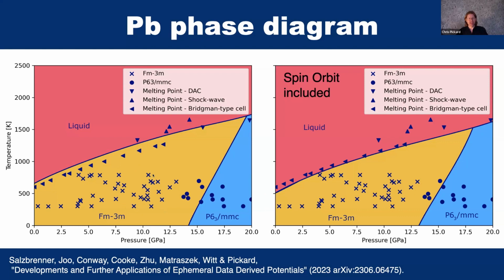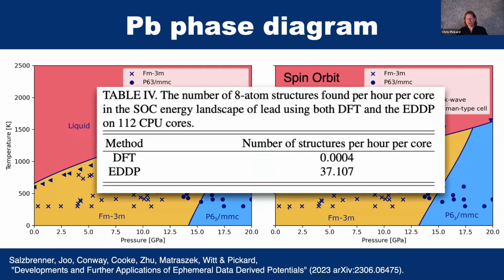So there's some experimental data here. It really maps out well that landscape. And what's really striking here is, even for just 8 atoms in a unit cell, the time ratio between using these machine learning potentials and using DFT. So we've done it in number of structures per hour per core if you're doing a structure search. And well, you don't really get any with DFT, but you get 40 or so with the EDDPs.